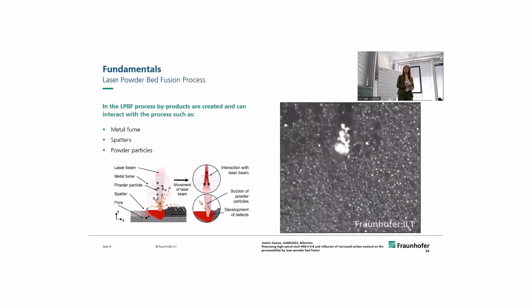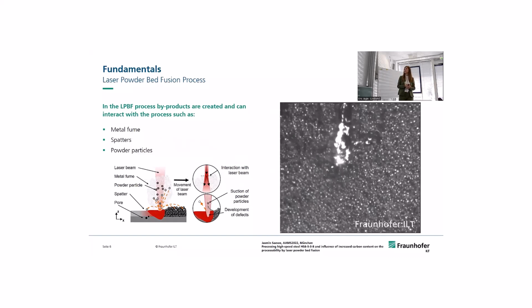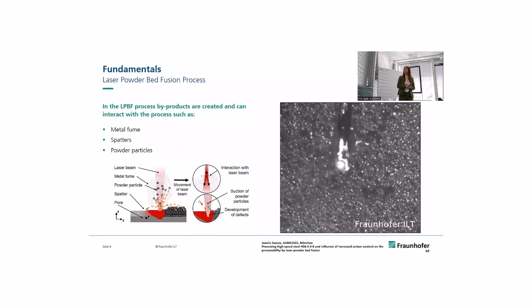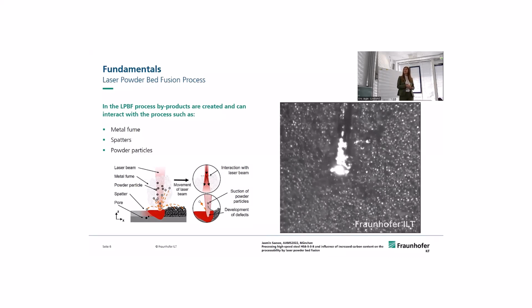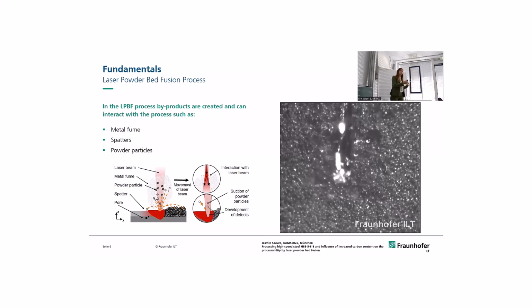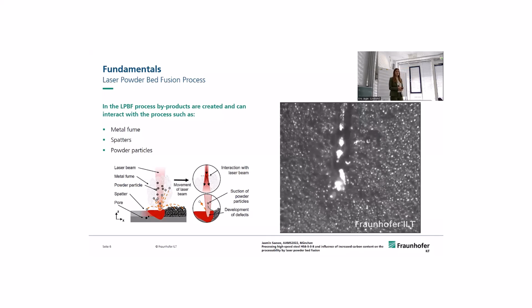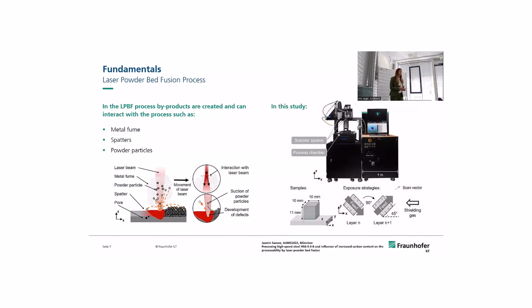Talking about shielding gas flow, just a little bit on fundamentals. We know that in laser powder bed fusion, we generate a lot of byproducts: metal fumes, spatters, powder particles, everything is moving. So maybe looking at the video will help a little bit. The powder is sucked into the melt pool, metal fume is generated, spatters are there, and the melt itself moves a lot as well. And we need the shielding gas flow to prevent any interaction of those byproducts with the laser,